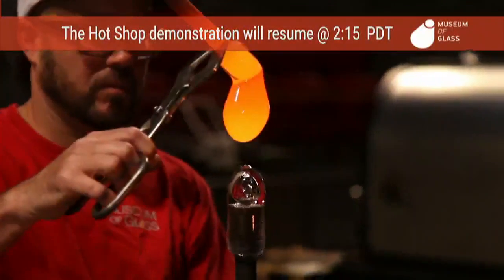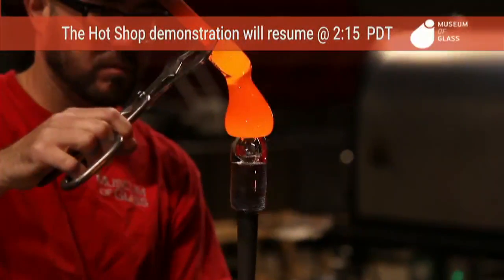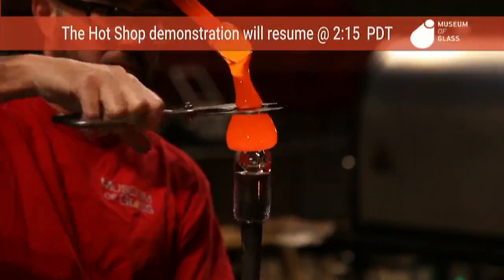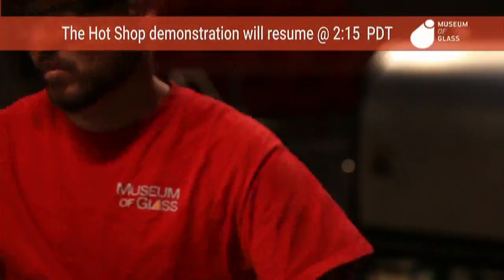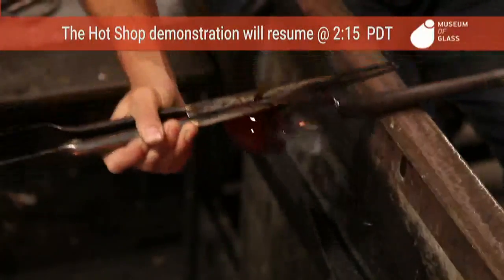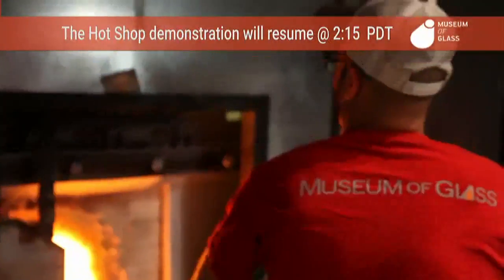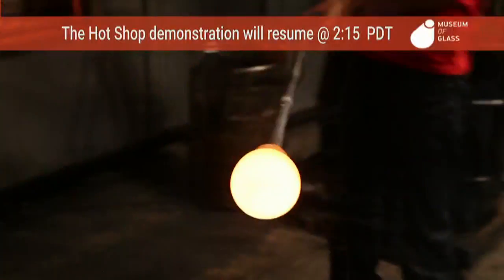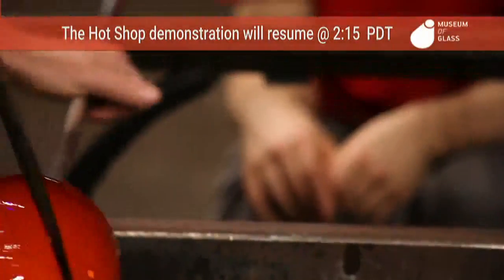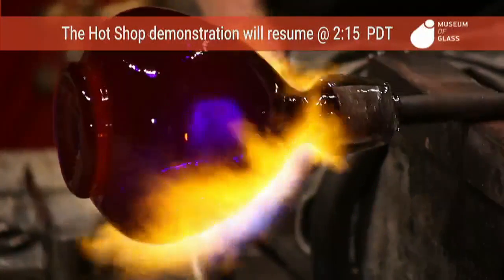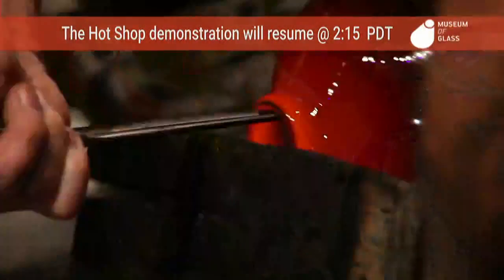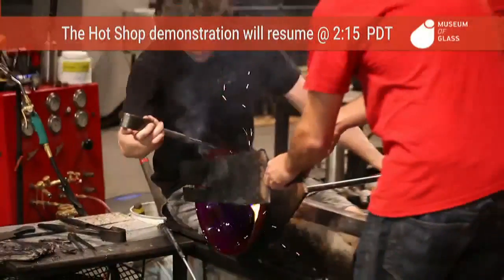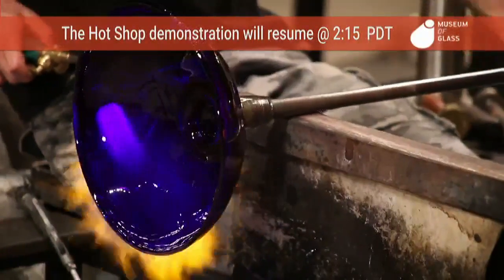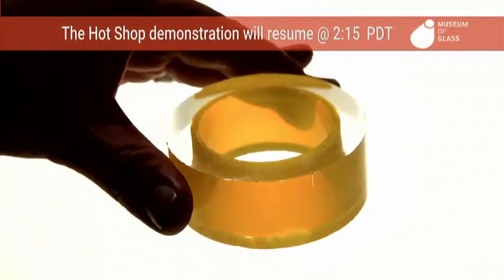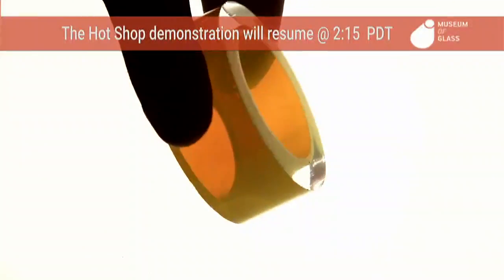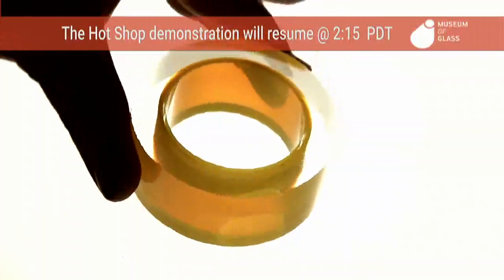Once warm, the color is dropped over the clear bubble, and then using a variety of hand tools or the steel marver, the color is rolled back over the clear in an even layer. This process is called dropping color, or creating a color overlay. Depending on the project, that bubble is then usually gathered over with clear glass and blown into the final form. The finished product may appear to be all made from colored glass, but when viewed in cross-section, we can see that there is only a thin layer of color sandwiched between many layers of clear glass.